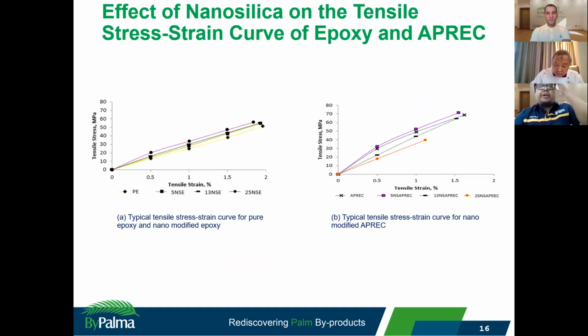In the first graph, you can see the increment of the stress strain curve starting from pure epoxy, and then when we add 5 weight percent nanosilica it also increases, and likewise at 13 and 25. But for graph B, the increment only occurred from pure epoxy to 5 weight percent nanosilica APREC. After we further embedded 13 weight percent and 25 weight percent nanosilica, the tensile properties of the composite specimen reduced.